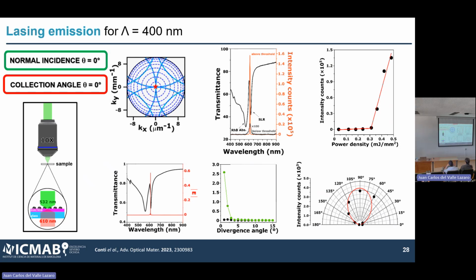And I'd like to remind you every time that I present the slides that all these points that you see here in all these 3 characterizations were taken from the same spots. So the system is actually quite stable, compared to other systems that photobleach, and this is possible because of the relatively low threshold. This is for people that work in lasing. When I say low threshold, they give me very angry looks. But let's say for a prototype system using colloidal metasurfaces, we were actually pretty happy with this value.